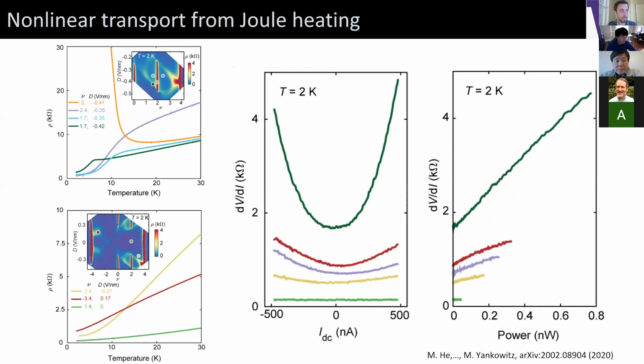Yeah, okay. Here you plotted dV/dI. What did the raw IV curve look like? We actually measure dV/dI. We're making an AC lock-in measurement. So you never change the amplitude of your AC current? We don't change the amplitude of the AC current. We're using a fixed and small AC current and then applying a DC current bias on top of that AC.